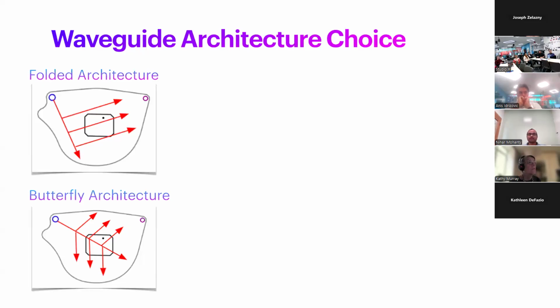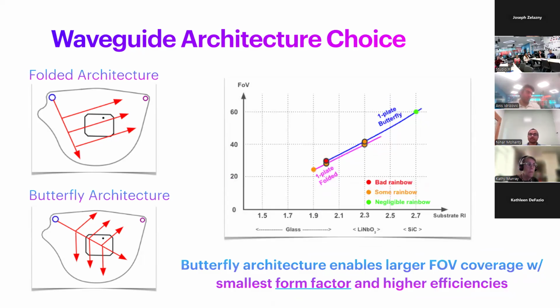Now that we identified the paths to reduce the rainbow, the next big challenge was the form factor. We wanted to make all-day wearable glasses, which means the premium on the real estate in front of your eyes was critical. There are two types of SRG grating architectures that can support temple-mounted miniature light sources: folded architectures and butterfly architectures. While the folded architecture is simpler and can be fabricated on a single side of a substrate, which is great for manufacturability, it is limited by efficiency, field of view coverage, and the desired form factor. Butterfly architecture, on the other hand, is much more complex, typically needs double-sided processing, but gives much wider design latitude for higher efficiency and field of view coverage at a much smaller form factor. We chose butterfly as our architecture of choice on silicon carbide to maximize the performance with a small footprint.